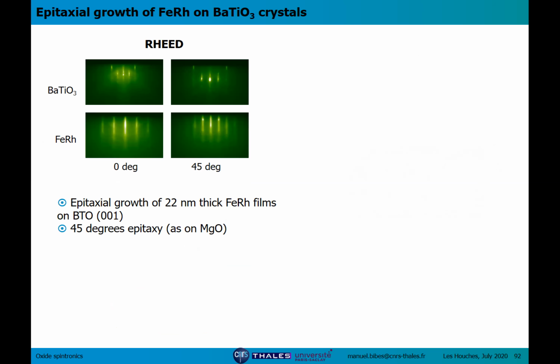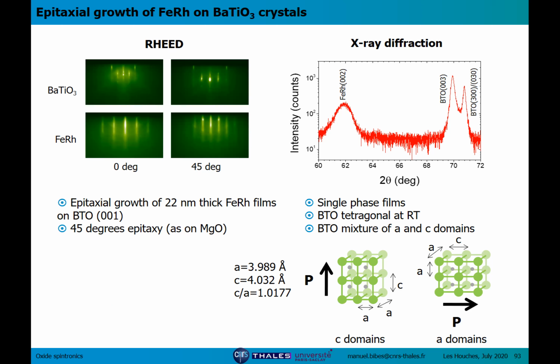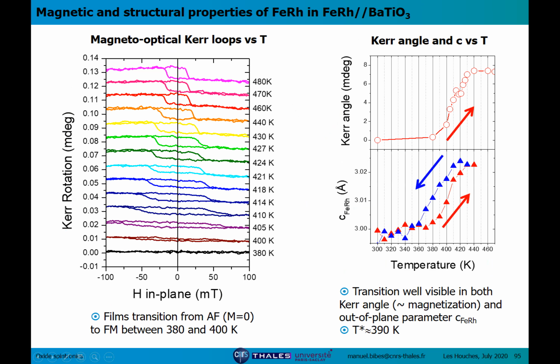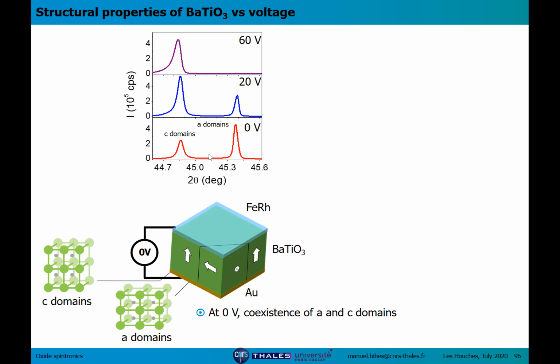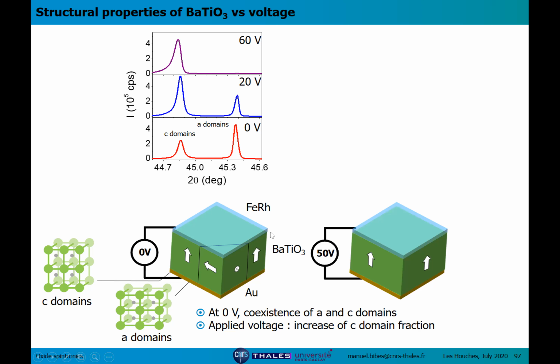So we grew iron rhodium thin films epitaxially on barium titanate. We wanted to see how the iron rhodium would behave when we apply an electric field to switch the domain structure of barium titanate from being mostly A domains to being mostly C domains. I want to go quickly through this. This is X-ray diffraction as a function of electric field. When we apply an electric field, the sample, which is initially a mixture of C and A domains, becomes essentially only C domains. So we go from this to that.